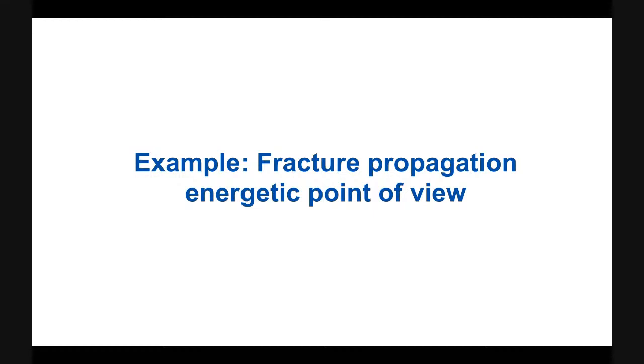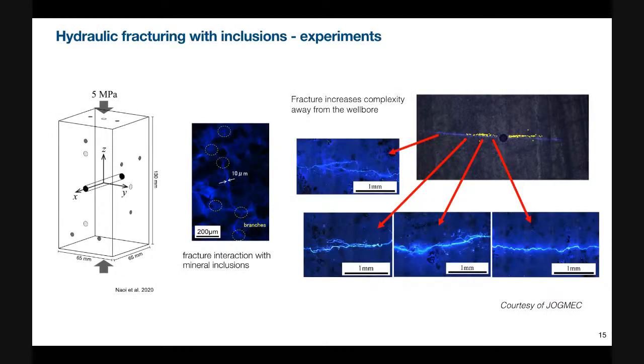Okay, so now we will look at some examples of fracture propagation from an energetic point of view. This is a hydrofracturing experiment done on a carbonate rock. We have this rectangular sample with a borehole drilled in the middle, and uniaxial loading is applied from top and bottom. Then there's fluid injection into this borehole, and a vertical fracture is expected because it is orthogonal to the loading direction. The sample is 97% calcite, so it's almost homogeneous. It has some mineral inclusions or grains, which are microfossils, and they are also made of calcite.